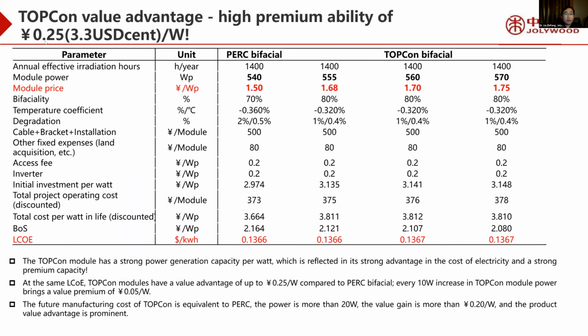And this is the TOPCon value advantage compared with the PERC. This is just a simple calculation. For the PERC modules, the module power is about 540 for the 182 silicon solar cell. For the TOPCon, the module power will be 555, 560, and 570. And some parameters such as bifaciality, temperature coefficient, and degradation are from the datasheet. And we calculate the LCoE.